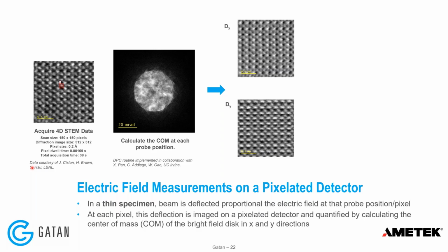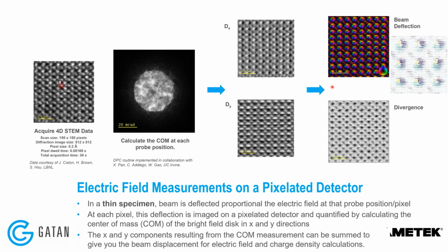So that is going to give you the dx and dy maps as you see here. These will be the two components of your beam deflection vector map, as I'm showing here in the color map. And then this beam deflection is related to the electric field in the sample, and by calculating the divergence of the beam deflection map, you can also calculate the charge density in your sample.